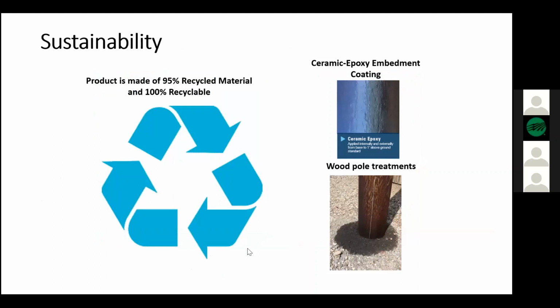Sustainability. A lot of times those wood poles are treated, so you can't really recycle them; many times they become scrap. Our ductile iron poles are made with 95% recycled material, and they're 100% recyclable at the end of their lifespan. We also put on a ceramic epoxy embedment coating. We coat the inside as well as the outside of the pole, and our standard is 1 foot above ground line.